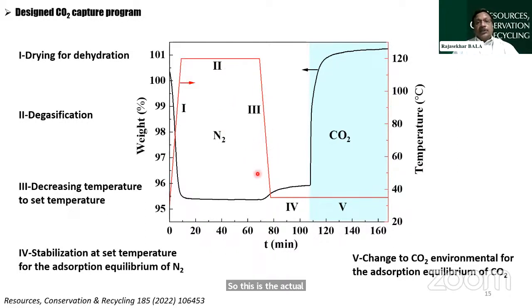So this is the actual adsorption process that takes place when you introduce carbon dioxide from the air into the material. We have carbon foam, and you could see over here, initially we are using nitrogen, and later on we are comparing it with carbon dioxide. Initially, this is the temperature regime, and you increase the temperature of the material, and then you basically volatilize whatever you have, in particular water vapor. Then you have a very dry material of carbon foam. Then you reduce the temperature down to 35 degrees Celsius, and then you could see the adsorption takes place for nitrogen. In other words, the weight of the material increases.